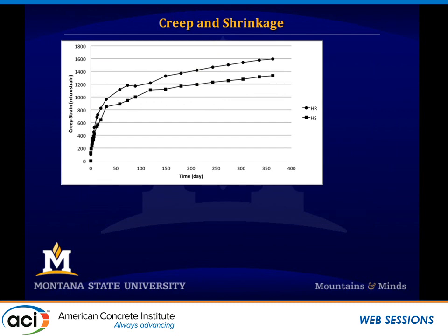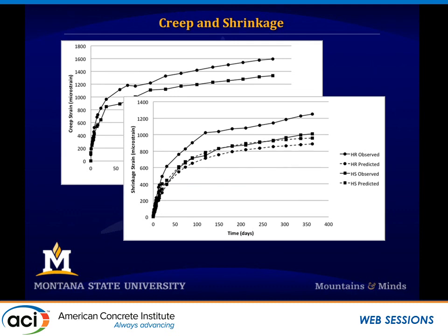Creep isn't necessarily something that's important in concrete pavements. It is in pre-stress and things of that nature, but in terms of pavements, it's not that important. But we had a creep frame, and we tested it, right, just to help quantify some of this stuff. And the high wrap creeped more than the high strength, and in terms of shrinkage, the high wrap shrunk more than the high strength mix as well, right? But it's also important to note that when we applied AASHTO equations for predicting shrinkage and creep, it was right on with predicting these things. So that's a little side note there.